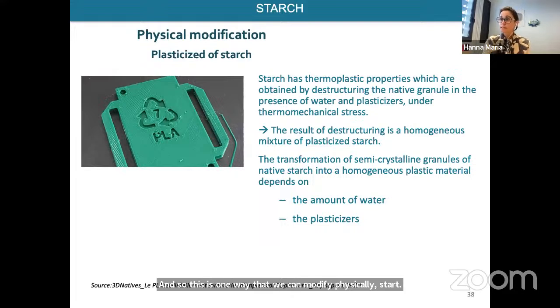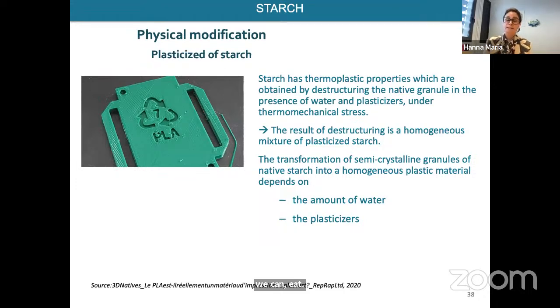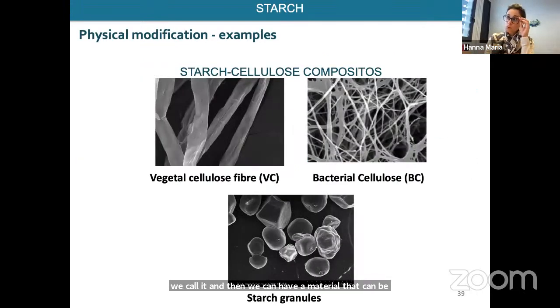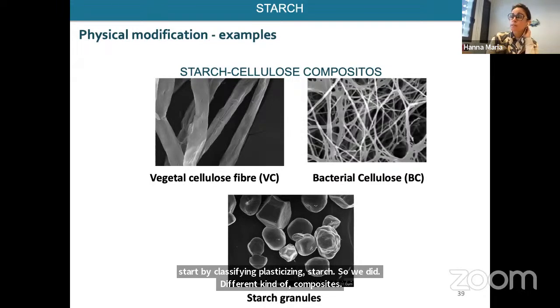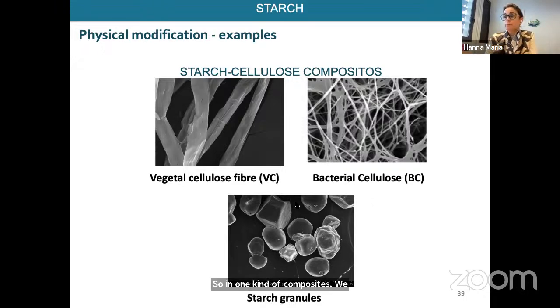And plasticized starch, so we can heat the starch up to 100 degrees Celsius, and then we can add different amounts of water, and we can use different plasticizers. Then we cool it, and we can have a material that can be flexible or not. So to give you some ideas of work that we did here in the lab by plasticizing starch, we made different kinds of composites. In one kind of composite, we used vegetable cellulose, from a hardwood, to make some materials.